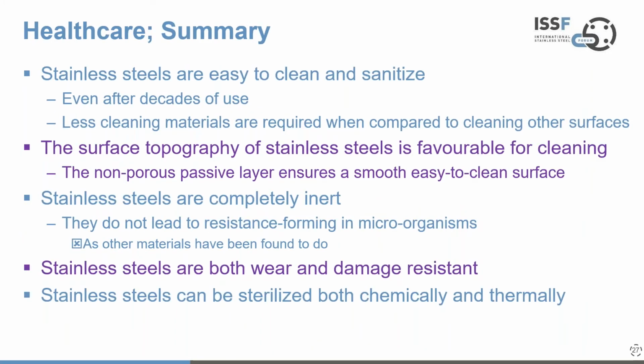So to summarize from a healthcare perspective, stainless steels are really easy to clean and sanitize, even after decades of use. Less cleaning materials are required compared to other surfaces, particularly those that are more susceptible to damage and or less smooth and hard. The topography of stainless steel is really favorable for cleaning, and the non-porous passive layer assists in that process. Stainless steels are completely inert, so they don't support the notion of resistant forming microorganisms, and other materials are known to do that. Stainless steels are both wear and damage resistant, and the passive film reforms in the case of damage, and both critical or widely used sterilizing techniques, either chemical or thermal, can be used on stainless steels with no ill effects. So a good all-round performance, although I must stress cleaning and sanitizing is an important part of working with stainless steels.